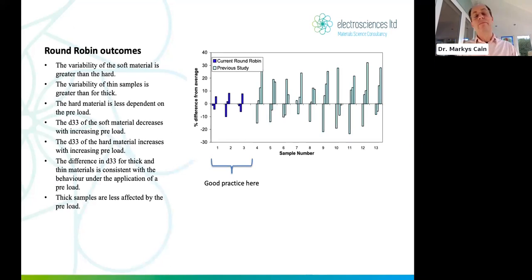The round robin I described earlier was where we sent off a bunch of samples to something like 10 different laboratories around the world and asked them to take measurements of D33 using their normal method. Then, between us all, we developed this sort of good practice in taking this measurement, like defining the geometry, defining the frequency, defining the preload, don't touch it with your fingers, getting it aligned centrally, and so on and so forth. And we asked everyone to do it again, okay, using an identical set of new materials, and using the good practice. And you can see that the variation, the difference from the average, so the smaller the better, is improved dramatically after following good practice. So the good practice I'm describing here has been proven and demonstrated on an international benchmark.